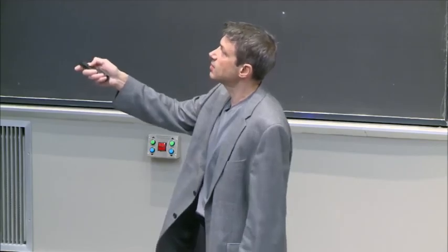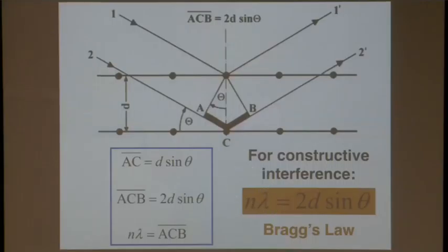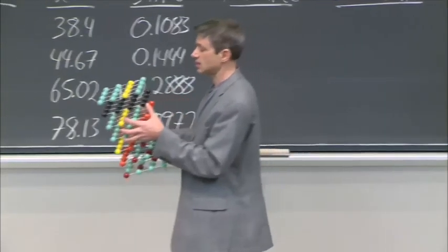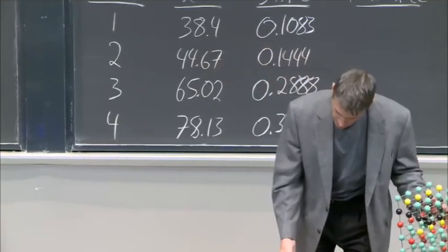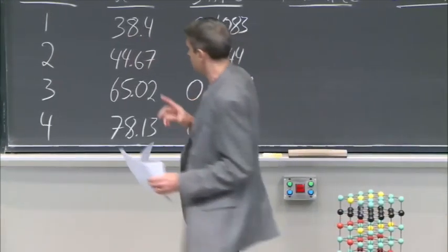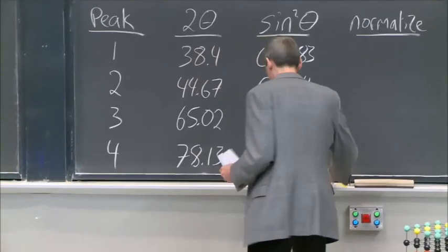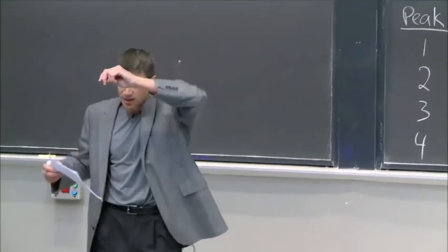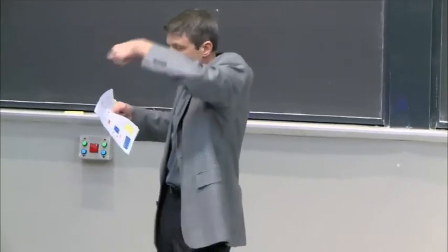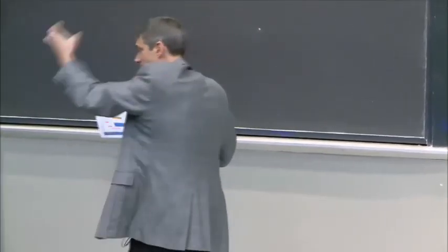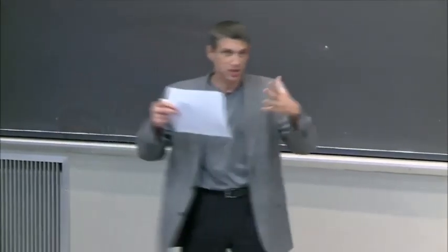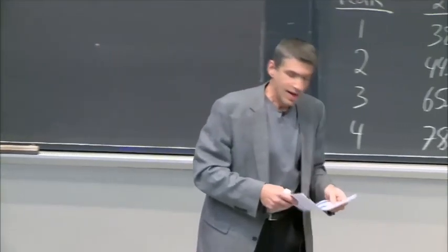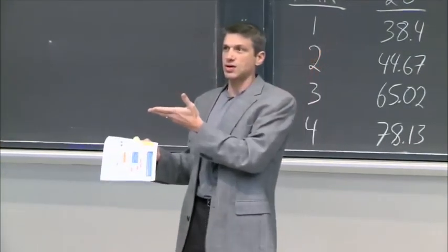That's the Bragg condition. And remember, in this class, it could be any multiple, but here we're just going to assume n equals 1 because it's the easiest case. Okay, good. That's the Bragg condition. Now, then we did something beyond just that, because that tells us what the wavelength has to be to get a spot, to get something the detector can see, because it constructively interferes. Everything else is destructive, no signal, right?